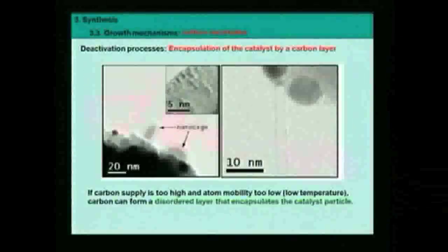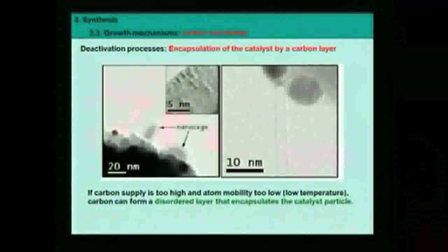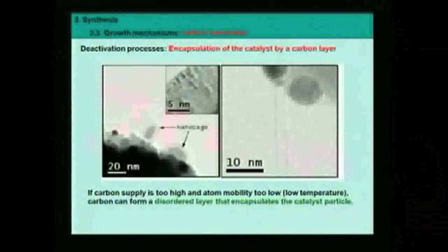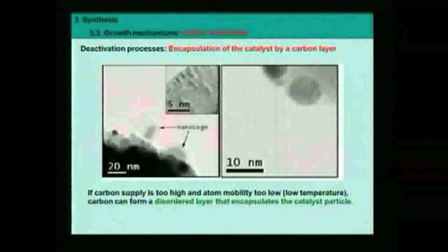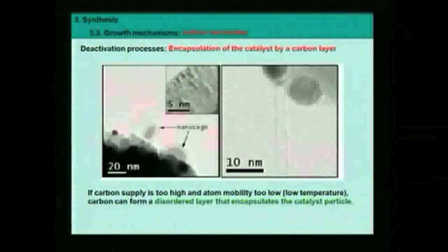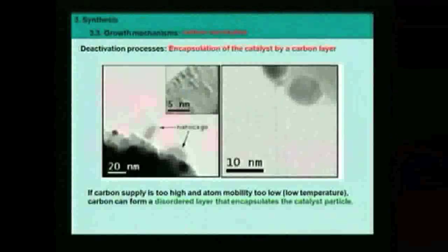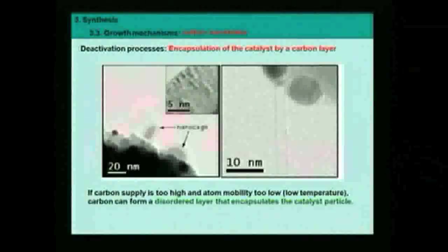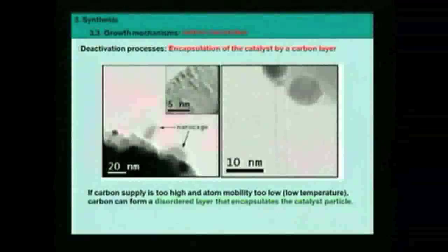So, the first example of deactivation is what I said. The particle could be covered by too much carbon, an excess amount of carbon. You observe here the particle, and there is a thin layer of carbon around, and this is due to too high an amount of carbon supply. If you provide too much carbon to the surface, and this carbon does not move quickly into the tube, then it will react with other carbon at the surface, you will reticulate this carbon network, and then you will encapsulate the particle completely. Okay? So to prevent that, you should not supply carbon too fast.